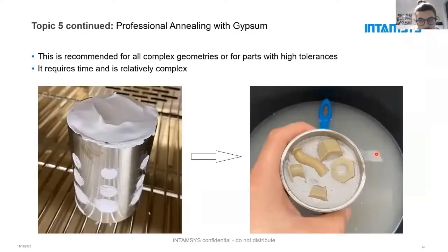This is definitely a process that costs for one container, depending on part size and container size, minimum 1.5 to 2 hours. But it gives you the possibility to have a very equal shrinkage. There is still a shrinkage in the part due to change of the structure, but the parts are shrinking very equally, so you have no risk of deformation within gypsum. There are other ways of annealing without gypsum, but with sand or with salt, but in our opinion, they have a slightly higher risk of deformation. So this depends also a little bit on your part geometry and on your requirements regarding accuracy of the part.